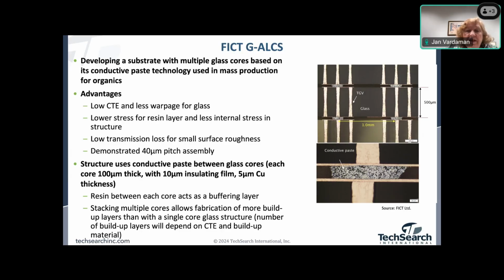They say that the conductive paste between the cores, each core being about 100 microns thick with 10 microns of this insulating film, 5 microns of copper thickness, that this resin is going to act as a buffer layer. And they say that they can stack multiple cores so that you can fabricate the buildup layers on this core structure. And I think they've done as many as like 3 buildup layers on that. So next slide, please.